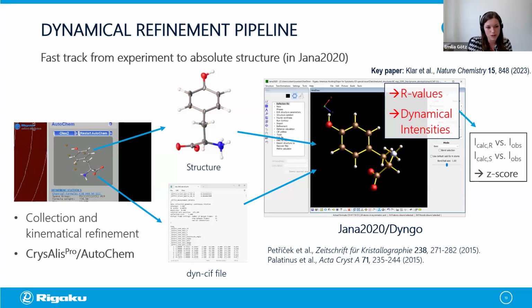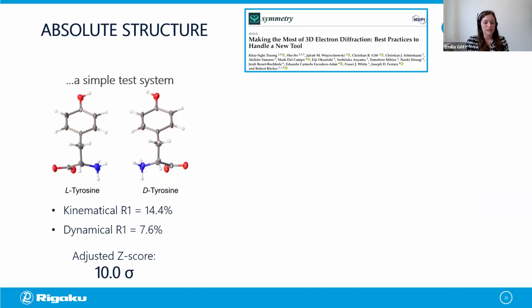If you want to know more about how this Z-score is calculated after the dynamical refinement, I recommend this paper by Palatinus et al., where everything is explained. But in short, a Z-score of over 3 sigma has an about 99% probability that said absolute structure is the correct one. So here we have examples to show this. This is an easy test sample, tyrosine again. First, we can see that the R value decreases significantly by about half after applying the dynamical refinement. And here we can see that we have a Z-score of 10 sigma, so it is extremely certain that the L-tyrosine is the correct absolute structure.